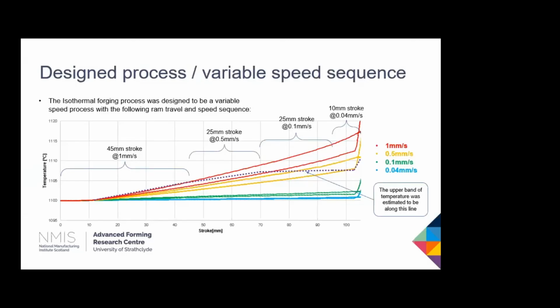So you can see in this case, this was our baseline at 1 millimetre a second. This was our baseline at the slower ones. But you can see if we went at those conditions, we don't go above that temperature threshold. So just by doing some intelligent modelling, we can maximise the die life, make sure that our material doesn't actually get into any trouble in terms of adiabatic heating.